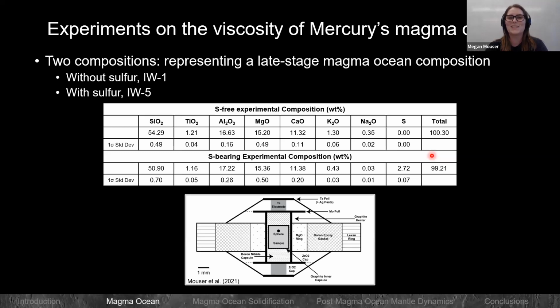Okay, so let's get into the experimental part of this. We tested two compositions that represented a late stage Mercurian magma ocean composition. One was with sulfur and one was without. If you remember, I said that there was a fair amount of sulfur on the surface. So we're testing the possibility that it was indeed part of the bulk composition, but also testing the possibility that it wasn't. And we're also looking at a range of relevant fO2 conditions, very reducing conditions for Mercury.